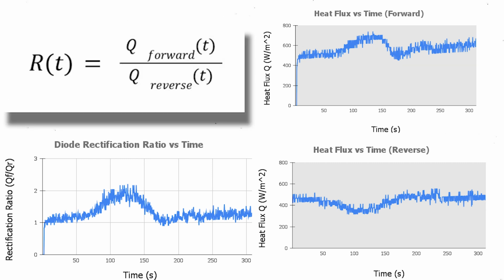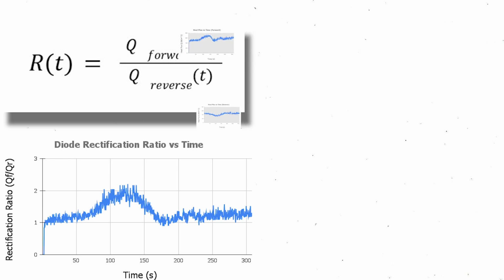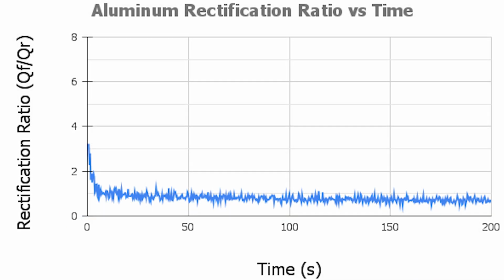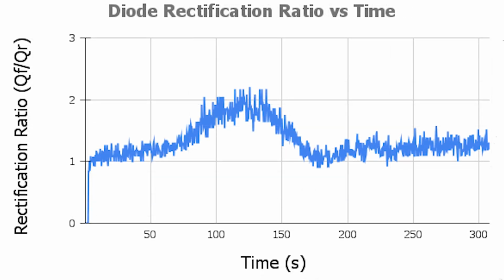Finally, the rectification ratio graphs use the forward and reverse heat flux. Aluminum is shown at a constant 1, meaning there is no directional preference for heat flow. But with the nitinol, we see a spike near its phase transformation temperature. That spike is key. It means nitinol resists heat more effectively in one direction, indicating a successful thermal diode effect.